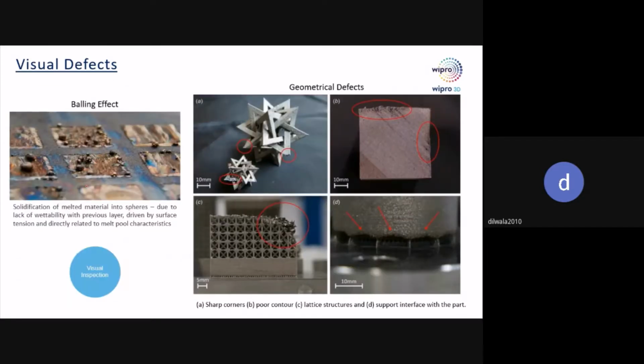Then balling effect. This is due to lack of wettability with the previous layer. Let us say this is my build plate and the laser is moving. If it is moving at the correct speed, then it will correctly melt all the powders and give a uniform layer thickness. Let us assume the scan speed is very high, so the laser moves very fast. Then what will happen? A certain amount of layer will be melted, certain will not be melted, certain will be melted, certain will not be melted. This is called the balling effect. Here it will be melted, here it won't be melted, due to high scan speed. So when the scan speed is high, this sort of balling effect occurs.